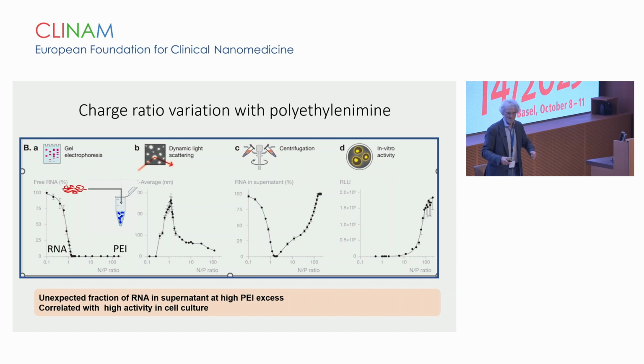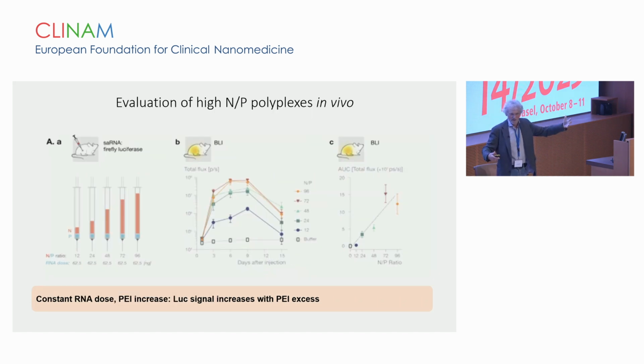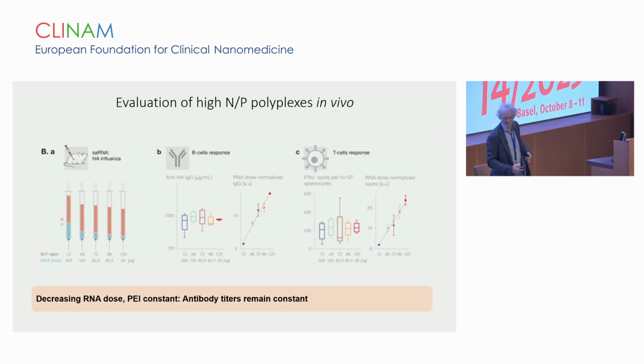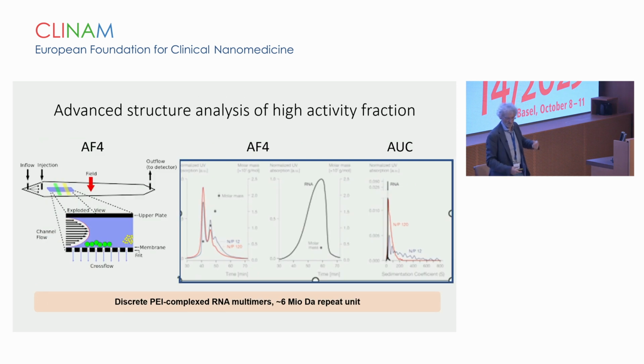And you can do then studies, and this is a very simple physical-chemical experiment where you mix the different components to each other. What has been found is that if you add a large excess of polymer to the RNA, you find a new phase of RNA complex with the polyethylenimine, and you can show that it has very high transfection efficacy in vitro and in vivo, and the activity increases with the excess of PEI, of the polymer. Now you could say, of course, there are these descriptions of excess being useful for activity, but it's something else. So that's all biological activity. We skip that for sake of time.